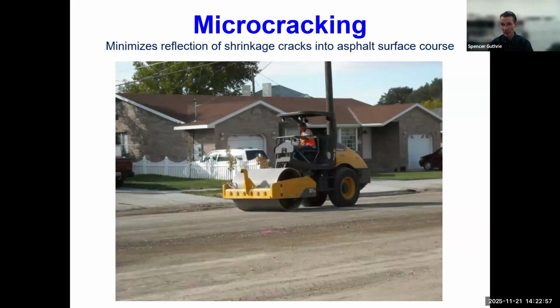Now, just like concrete, cement treated base also shrinks a very tiny amount when it cures. To accommodate shrinkage in concrete, think about sidewalks, we deliberately install joints. We perforate the concrete, if you will, forcing it to crack at specific locations with a more desirable geometry so that they're straight cracks, right, and they're easier to maintain. We don't do that for cement treated base. And if we don't intervene, it will crack on its own approximately 15 to 30 feet down the road. And those cracks will often reflect into the asphalt. I'll show you a picture.